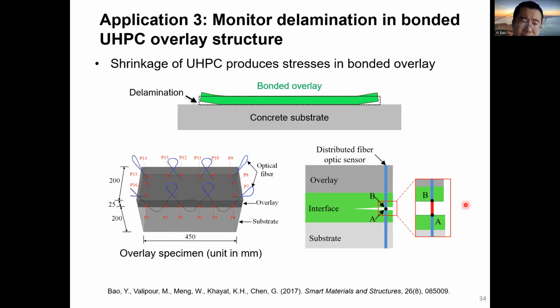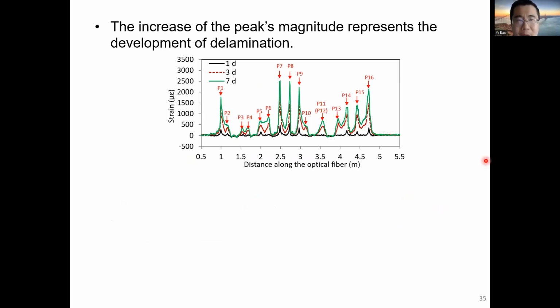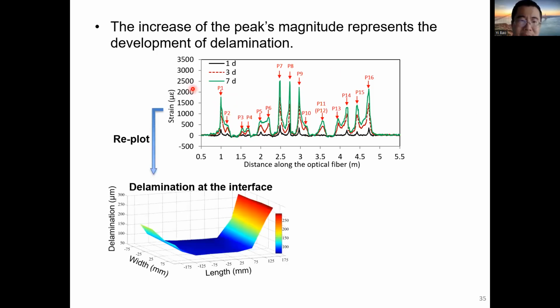Well, this installation method could be modified in real applications. For example, we could increase the distance, or the spacing, between adjacent intersection points, and then the whole fiber optic cable could be embedded inside the concrete. The key point is that the fiber optic cable can sense the strain distributions along the entire length, and the delamination points could be detected as sharp peaks because of the discontinuous strain field. And this strain distribution could be replotted to show the delamination condition because we know the positions of the intersection points in the physical specimen.